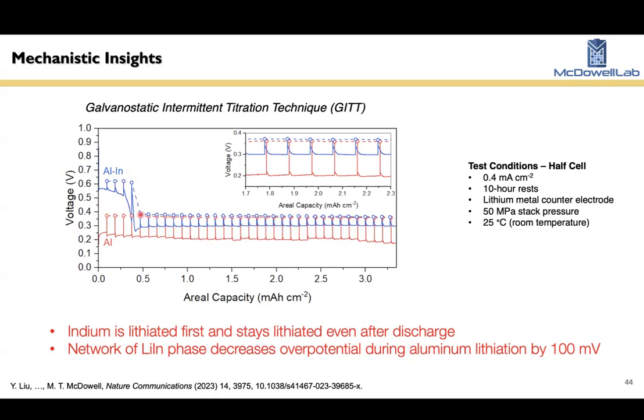The indium aluminum is interesting. So first, what happens is the indium within the foil reacts. That's this higher plateau here. So the indium completely transforms to lithium indium. But then during the aluminum lithiation down here, this blue part, it has a much lower overpotential, much lower than the pure aluminum. So the presence of the lithiated indium in the cell is significantly reducing the overpotential of the aluminum reaction.